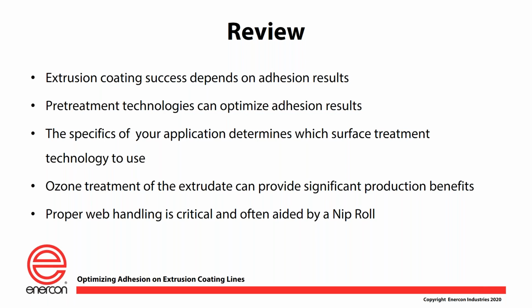And just a few points to review. Extrusion coating success is dependent on your adhesion results. That's the true measure of success. Pre-treatment is used in several different areas on an extrusion coating line to optimize adhesion results. Your application, the type of film or paperboard that you're using, the line speeds that you're running, all combine to help determine which surface treatment technology is best to use. Ozone is a proven treatment method at the extrudate, and it can provide significant production benefits in both bond strength as well as operational benefits relative to speed and temperatures.